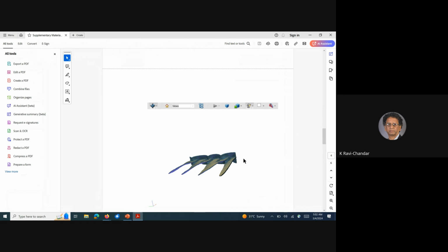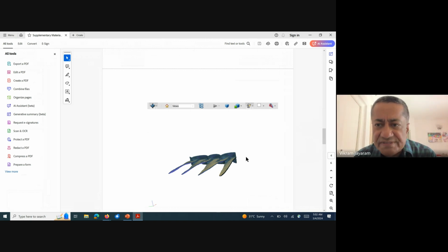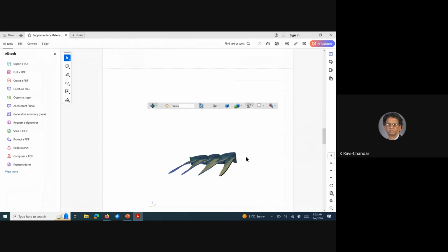One question from Ravi. Thank you, very interesting. I missed the first part, so I don't know if this is relevant, but there seem to be similarities with ordinary cleavage fracture, where a cleavage plane at a grain boundary has to branch. Very good observation. I should have pointed that out. There are some very elegant experiments by Ali Argon, where he looks at a cleavage crack in one grain meeting another grain where the cleavage plane is misoriented. As they pass through, they create the same system of echelon cracks in the second grain. And it's exactly the same mode 1, mode 3 interaction, because if it's mode 1 in the first grain, along the cleavage planes of the second grain it's a combination of mode 1 and 3.